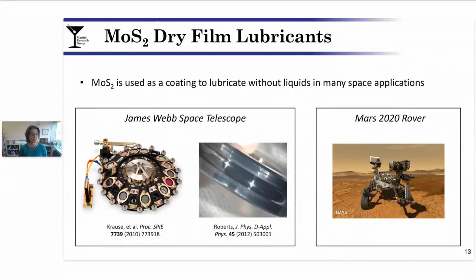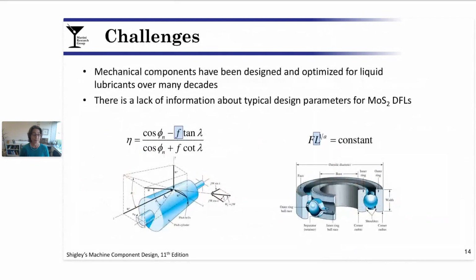MoS2 dry film lubricants are already used. Again, these are coatings or solid lubricants that are used without liquids. A couple examples are shown here. On the left, you see photos from the James Webb Space Telescope and an MoS2 coated bearing. On the right, you see the more recent Mars 2020 rover, where the sample caching system, the actuating components in the sample caching system relied upon MoS2-based dry film lubricants. However, there are significant challenges.